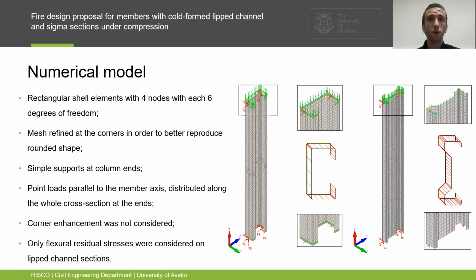Shell elements with 4 nodes, with each 6 degrees of freedom, 3 translations and 3 rotations, applying the finite element software SAFIR, were considered. The mesh was refined at the corners to reproduce the rounded shape, simply supported at the ends. The loads were applied parallel to the member axis at the ends according to the linear stress distribution presented. This study did not take into account the corner enhancement resulting from the manufacturing process, and only the flexural residual stresses were considered.